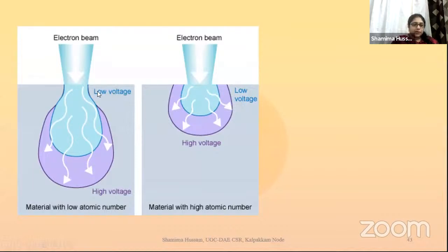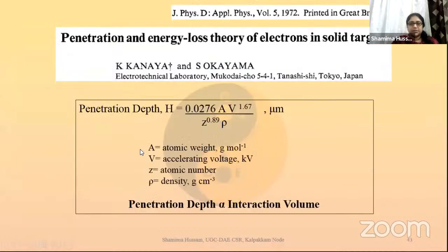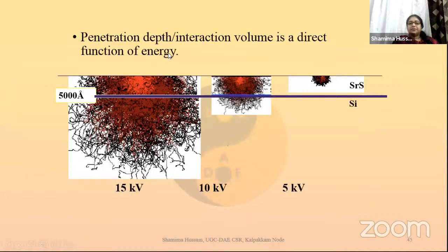When I have a low accelerating voltage, the interaction volume comes this way. For high voltage, it penetrates this much. And again here, with a high atomic number, the spread is higher. With a low atomic number element, the spread is lower. If I were to see it here, this is how it comes. Penetration depth: please see here that this is a 15 kV acceleration voltage. The penetration volume is huge. 10 kV is small and 5 kV is even smaller, right?